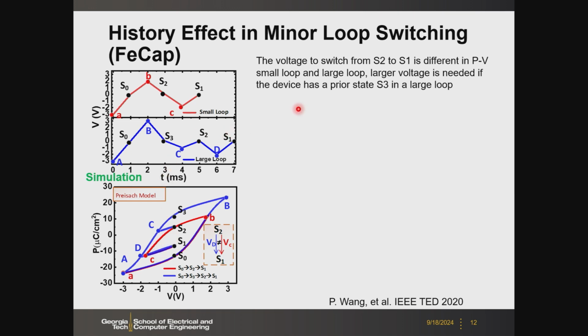So if you want to tune the device into an intermediate state, for example, you have different trajectories here to program the device from, let's say, S0, the ground state, to different intermediate states. So this is by simulation first, based on the typical Preisach model. And we have the bigger loop, which is the blue curve. Let's say we start from S0 and then program the device to S3, and then we switch it back to S2, and then we switch it back from S2 to S1. Okay, so this is the bigger loop.